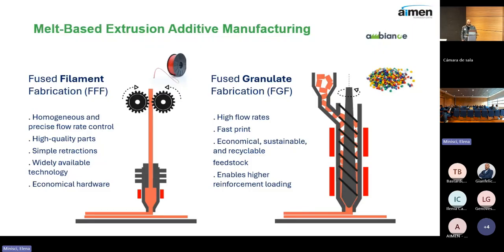On the other side, we have the fused granulate fabrication. It's not so common. It's more focused on high deposition rates to create very large parts. The feedstock, instead of the filament, is kind of a chopped filament in the shape of pellets, like lentils, small balls, small cylinders. It's more economical generally. It's more sustainable and recyclable because the feedstock does not need the filamentation process, which is quite complex due to the very high tolerances that the filaments need to have to be well processable by filament extrusion.